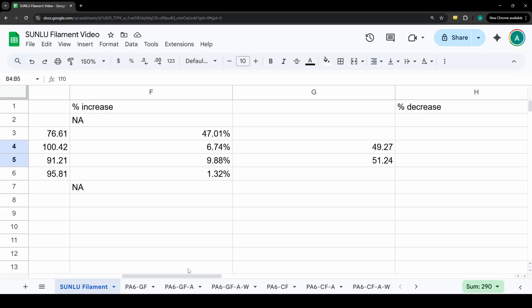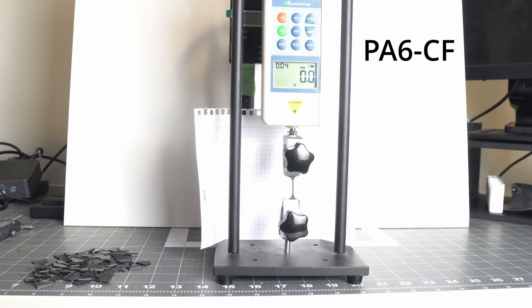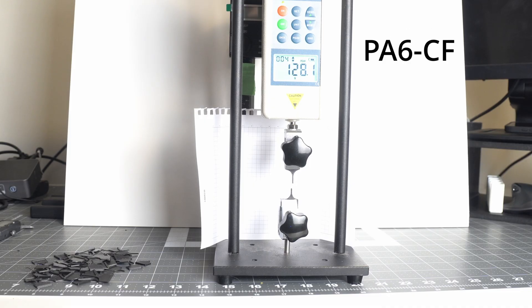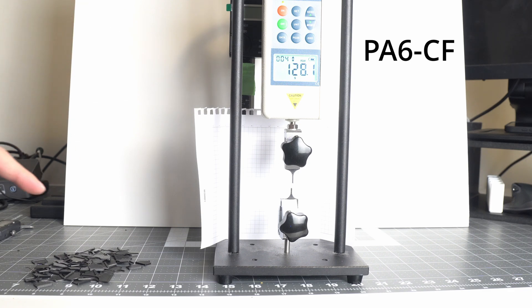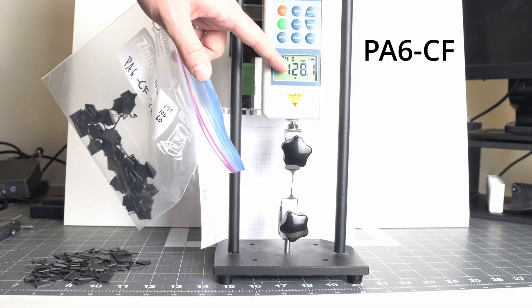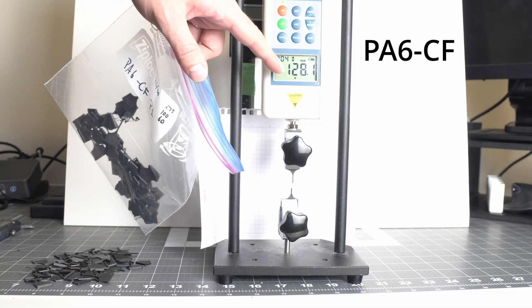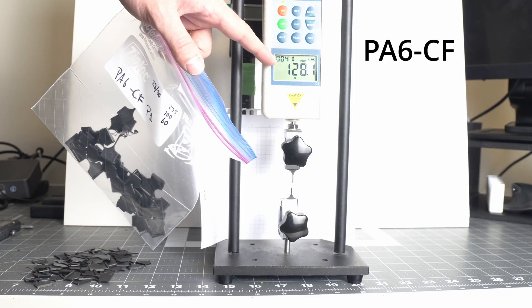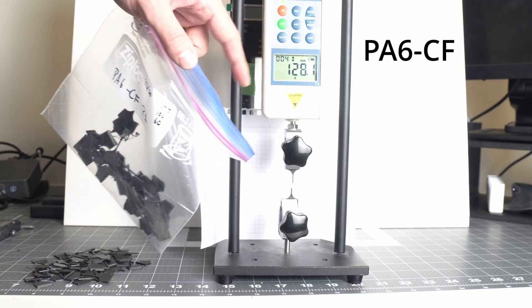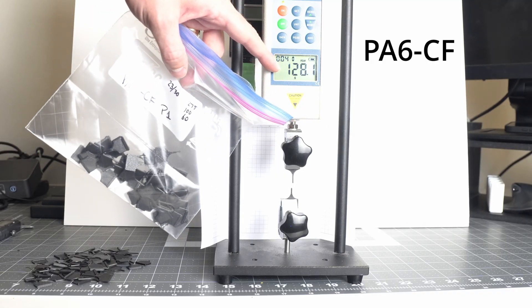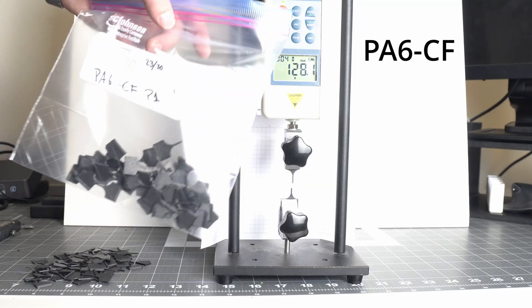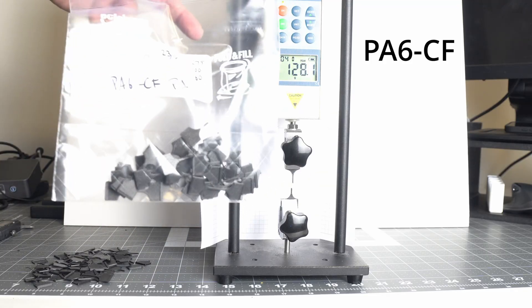But all hope is not lost. I filmed a lot of the sample pieces a week after I'd actually done the official sample tests and this is what happened. PA6 carbon fiber as printed, 128.1 newtons. Wow okay, this is really interesting. These PA6 carbon fibers that I printed probably about a week ago, I did them directly off the printer and I got much lower numbers. I was getting in the 100 newton range or just above, 105, 106. Now I'm getting 128 and the previous one I think was 126, which is much more in line with the data sheet.